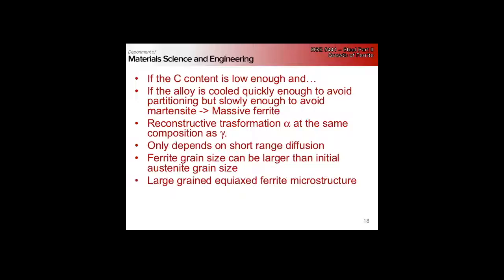And you need to have it be low enough temperature that you have enough driving force for it to happen quickly enough without partitioning. Here you need your transformation to be faster than the diffusion of the carbon.